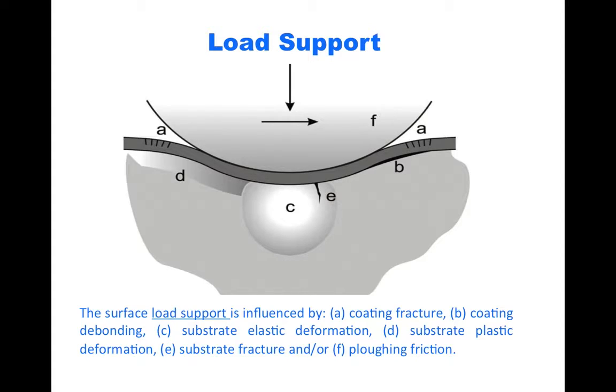So load support's important. So that's one thing that I believe is important as you develop new coatings, is to consider the underlying substrate and the coating as a system, not just a coating. You'd be surprised how many papers we get to my journal. I've done a hard coating on titanium to improve its wear resistance. No, you haven't. And then they do a test at a few grams to prove that this coating can survive. But then no way would it work on a real tribological load. So you do need to have the load support.